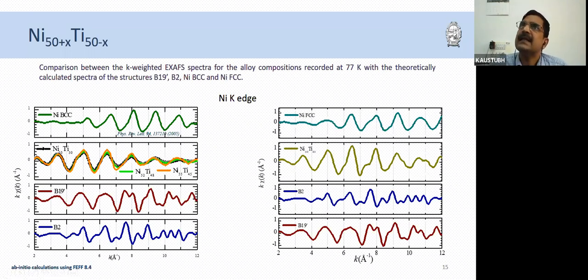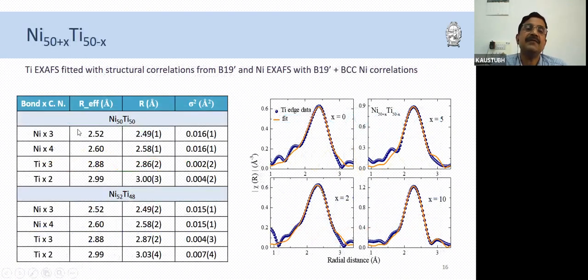So we thought, okay, in nickel 60 titanium 40, we have a face-centered cubic structural phase of nickel, which we can see from XRD. So the same story should happen also in this alloy. And we can see that there is quite a good match between the FCC nickel EXAFS oscillations and the oscillations in the nickel 60 titanium 40, especially at 8 angstrom inverse and above. So we thought, okay, now we have a model, and we fitted titanium EXAFS with the structural correlations from B19 prime, and nickel EXAFS with correlations from B19 prime plus body-centered nickel. And we could get a very good fit here.